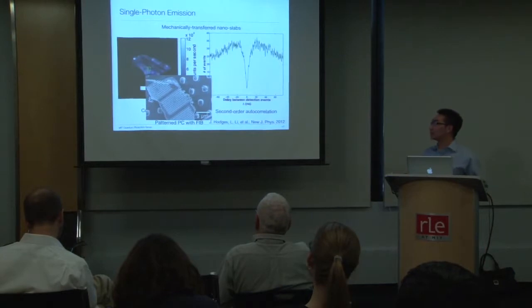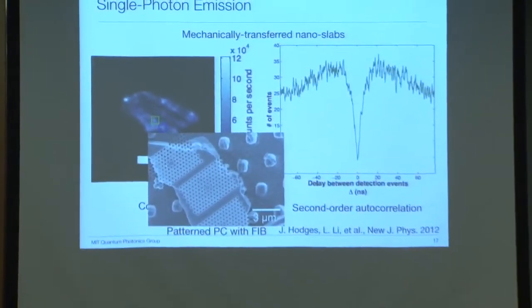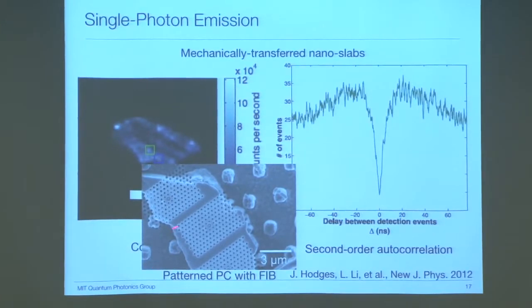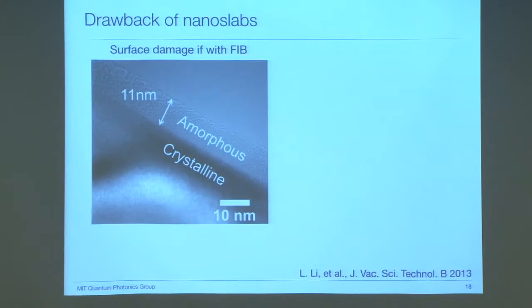These membranes are also large enough for us to pattern photonic crystal cavities. This image gives you an idea how we pattern photonic crystal cavities with focused ion beam milling. We also call focused ion beam FIB. Unfortunately, these cavities do not give us any cavity resonance. That's because FIB causes surface damage, as you can see in this image.